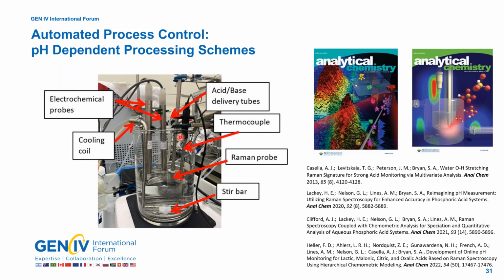And right here, I'm pointing out the Raman probe in solution. And we have adjacent to that some electrochemical pH probes, so we can measure the pH in a secondary form. So we have a secondary form for confirmation. And we also have some acid-base delivery tubes in solution. So we have this set up controlled by a PLC controller. We're monitoring pH, and we're going to allow the PLC controller to automatically control the pH by adding either acid or base through acid-base delivery ports, tubes, to maintain the pH at a set point.